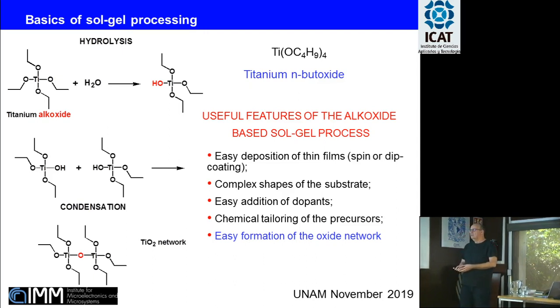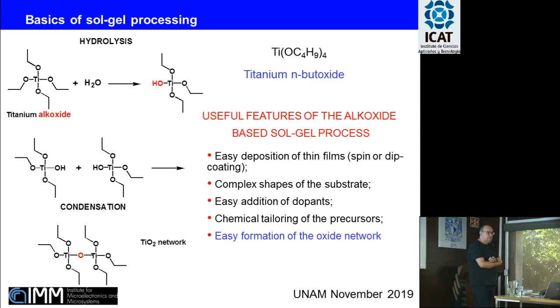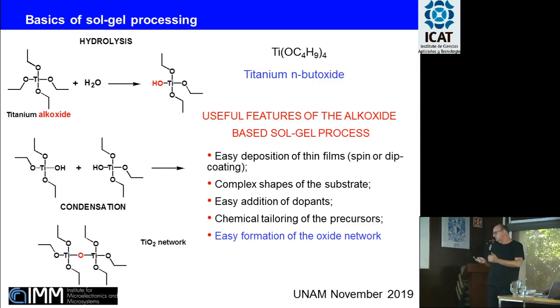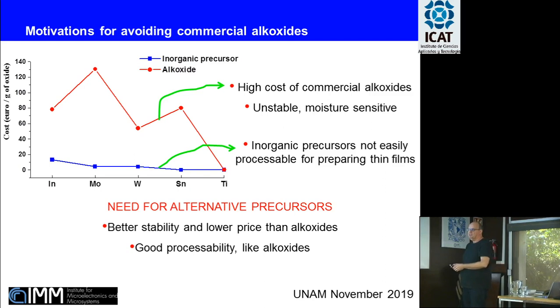We can easily deposit thin films, as I was saying before, by spin coating or dip coating. We've always been using spin coating. We can think to deposit onto complex shapes of the substrate. And again, we can introduce additional dopants, and we can chemically tailor the precursor. We can carry out many interesting chemical modifications of the structure of the precursor. And there is easy formation of the oxide network. Hydrolysis and condensation are carried out very, very rapidly, even at room temperature. So we don't need, in principle, to carry out very complex reactions to get an oxide network. The most difficult thing is to carry out a heat treatment after the synthesis for crystallization of the film. But the Sol-Gel process seemed very much interesting as concerning the possibility of preparing thin films.